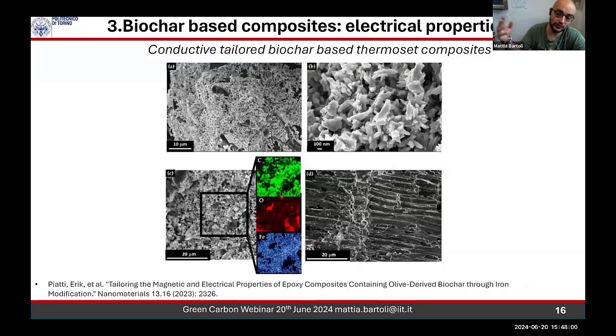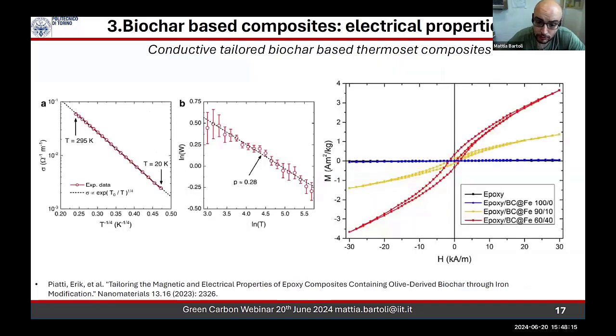Of course, you can enrich the overall process because you can pair the electrical conductivity with magnetic properties. Here we used olive residue, tailoring heat with iron particles to produce a conductive biochar that also shows magnetic properties. And we moved these magnetic and electric properties to composites. So we obtained a composite that at the same time shows magnetic and highly conductive properties. So you can have smart materials in this way, tailoring heat, using the appropriate temperature, and so on.